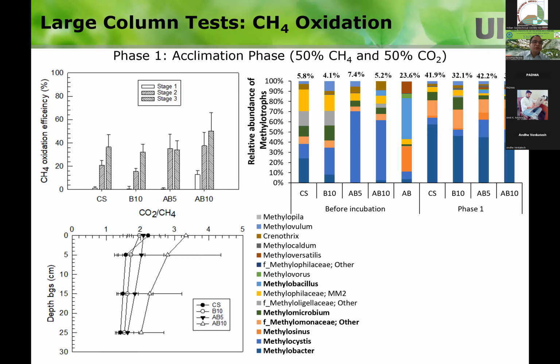CO2 to CH4, the ratio of them at the inlet is 1. And then if you see the ratio is more than 2, 3, what does that mean? Most of the methane is converting into CO2. The CO2 amount is more, so the ratio is high. So again, from the gas profiles, you can understand that.